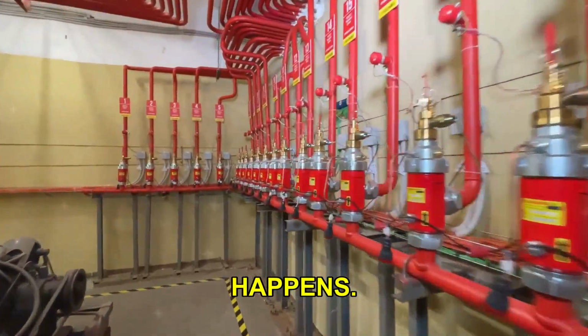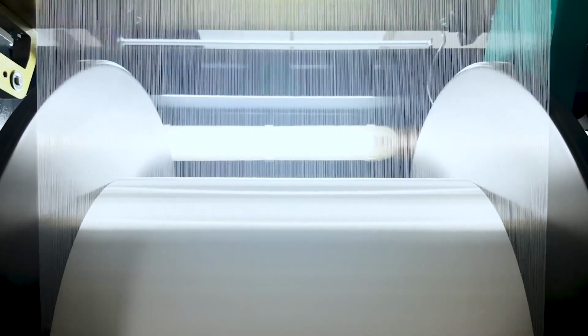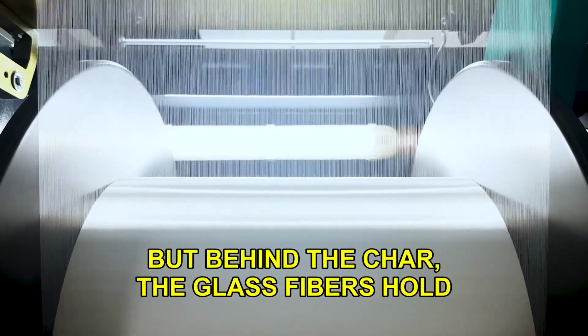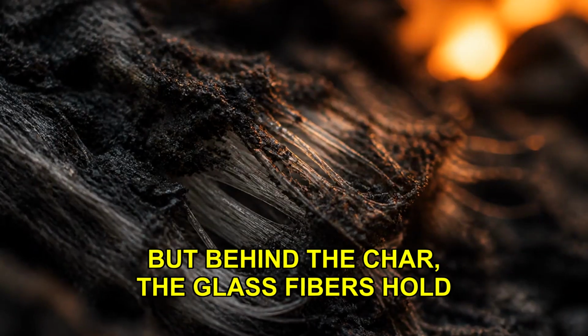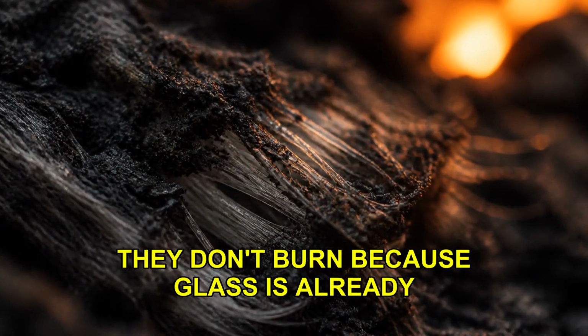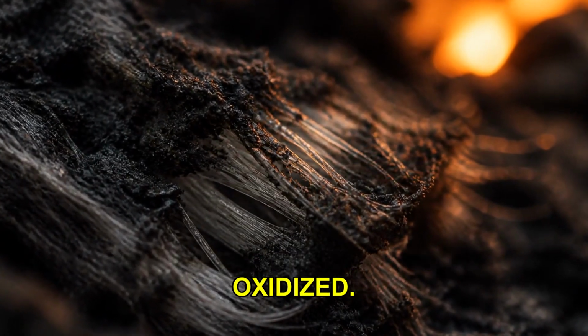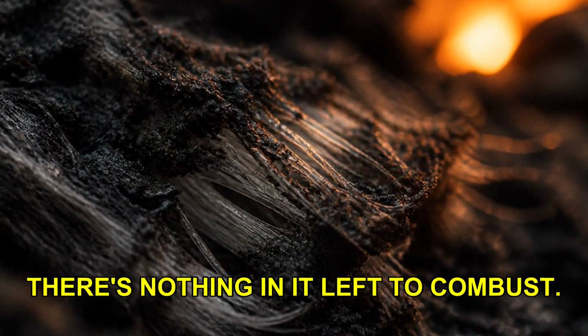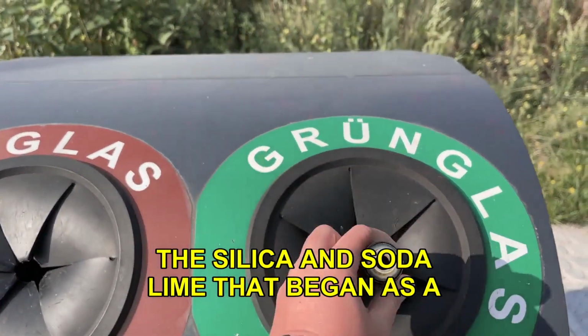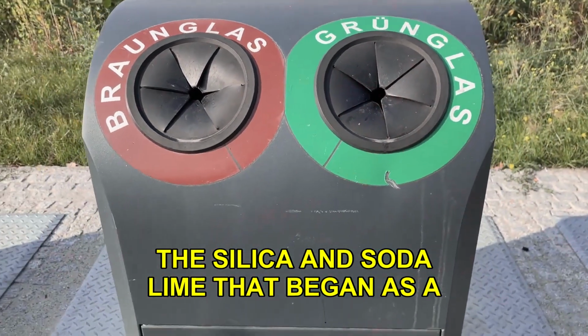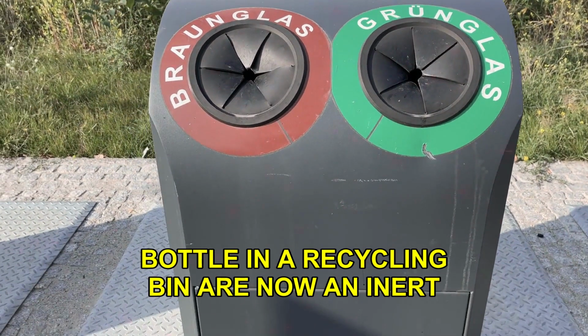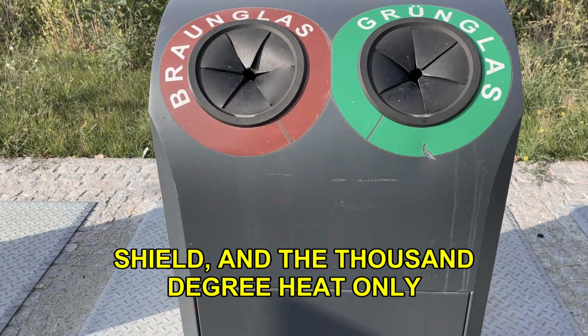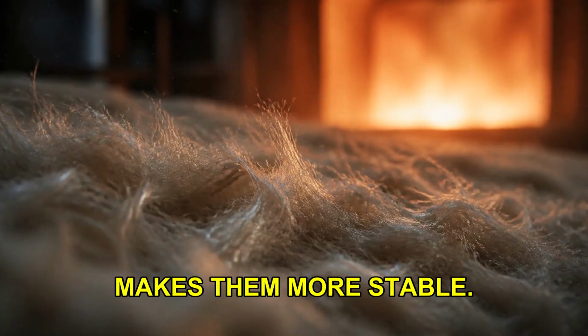For the first 20 minutes, nothing visible happens. The pink blanket darkens. The paper facing vaporizes. But behind the char, the glass fibers hold their shape. They don't burn because glass is already oxidized. There's nothing in it left to combust. The silica and soda lime that began as a bottle in a recycling bin are now an inert shield, and the 1,000-degree heat only makes them more stable.